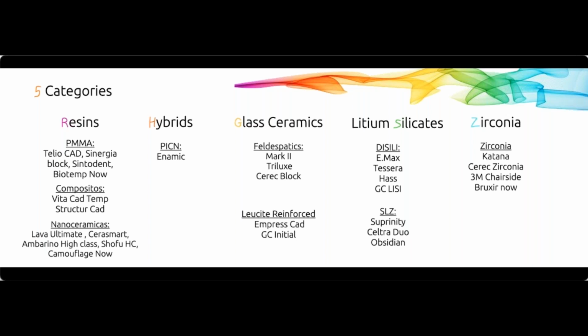That is a scientifically true fact, that in the actual online course, I go through all the literature and I'll show it to you. But one of the biggest negatives of zirconia is you can't see through an X-ray. You can't see zirconia through an X-ray. Every other material, I can see underneath. I can see if there's a bubble. I can see if the cement is washing off. I can see if decay is starting, because you can see through it. With zirconia, we're back to PFM, where you only see secondary decay once it spills over. So I think that the benefits of using zirconia are not outweighing the negatives, which is you can't see through an X-ray, and you can bond as well, some studies show.